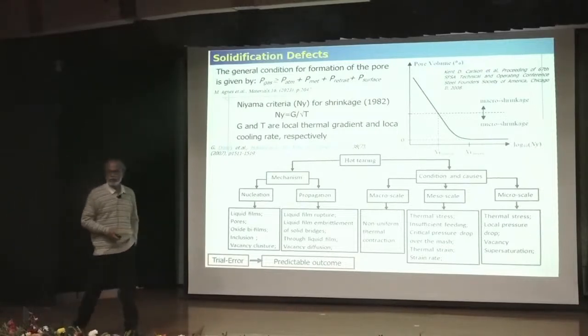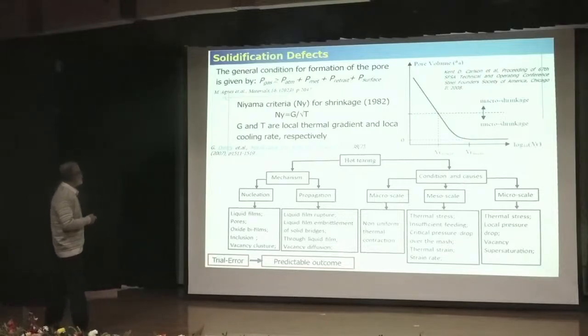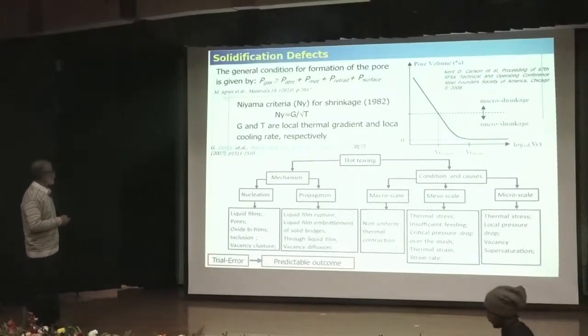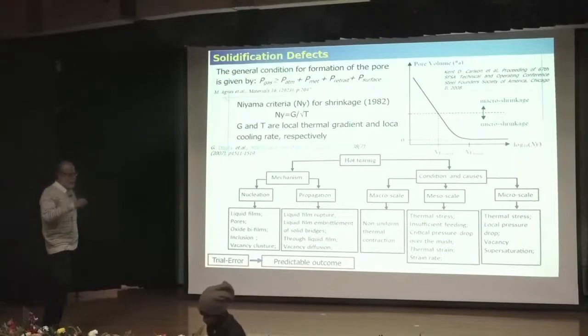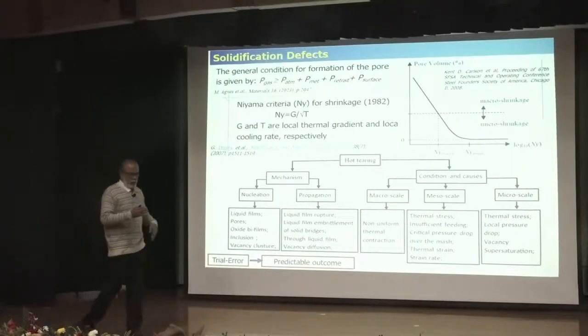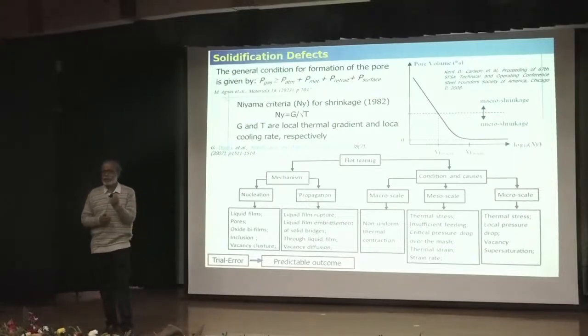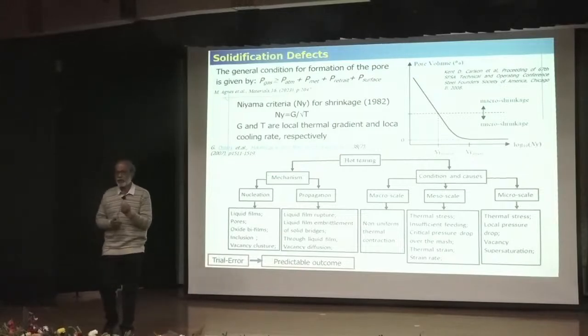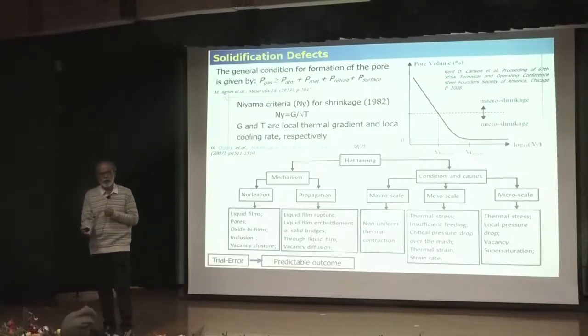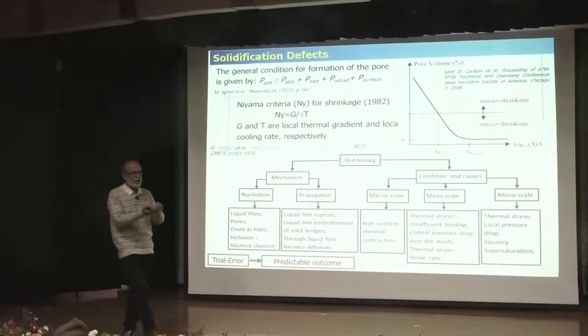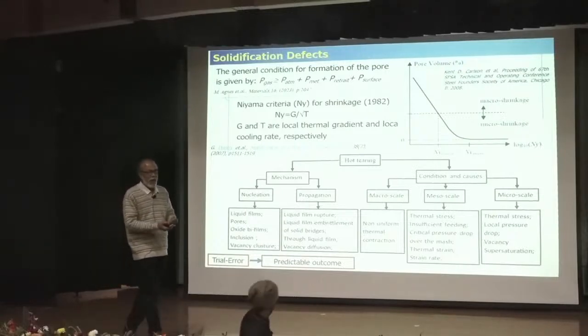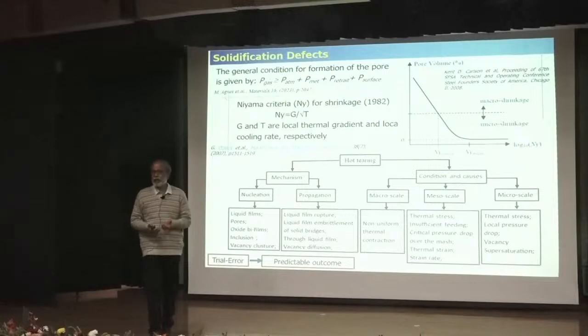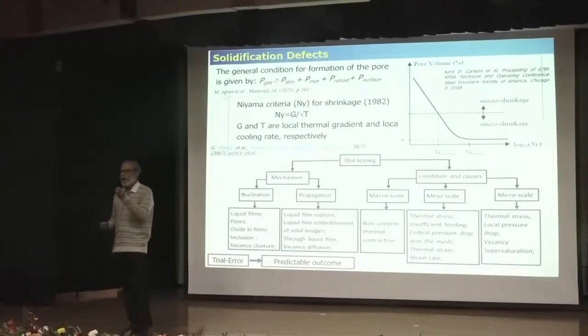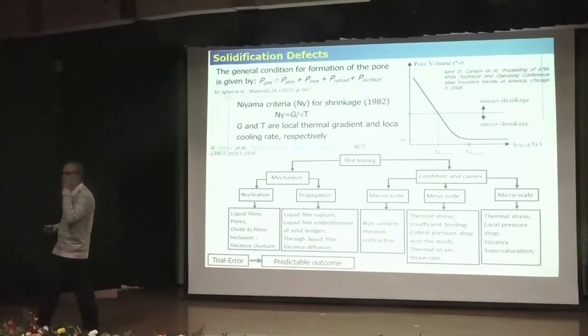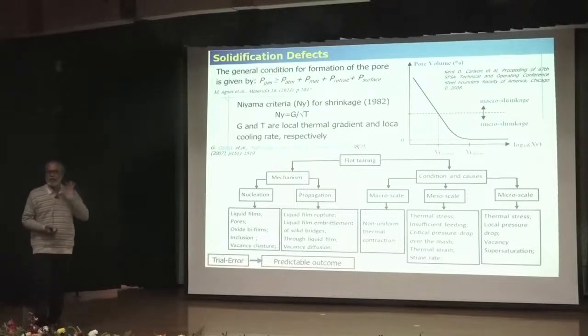This is a non-continuum system. So people tried to understand, and this is the region where during solidification there is a shrinkage in the solid. Once there is a shrinkage in the solid, there is a drop of pressure in the liquid. Once there is a drop of pressure in the liquid, there is a reduction in solubility of gas, and it gets supersaturated, it evolves gas heterogeneously, and that gas creates nucleated bubbles, and they remain within the liquid, and that is the source of porosity.